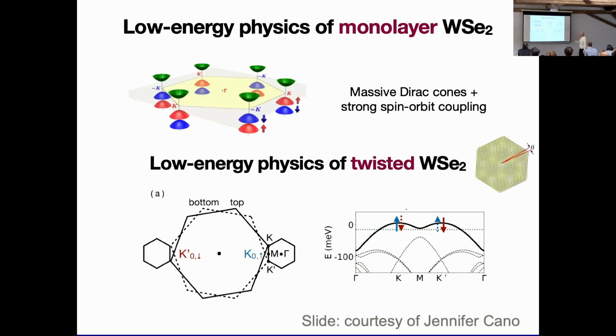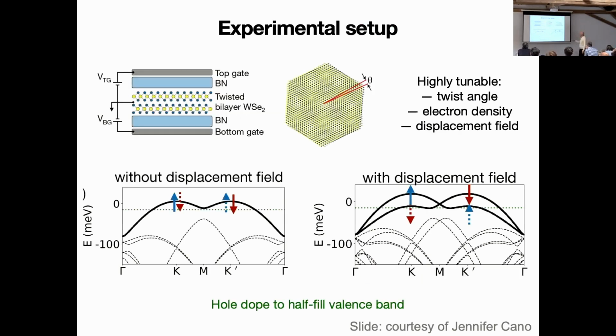And you know, this is the effect of the displacement field. With zero displacement field, you have a single band. With displacement field, you lift the degeneracy. And the bands, because of the spin-valley locking, have a definite spin character. At the end of the day, you get this moiré-Hubbard model with a tunable phase.